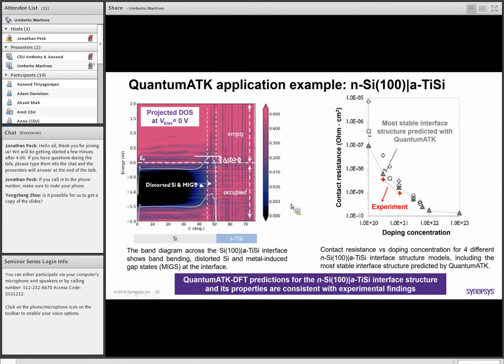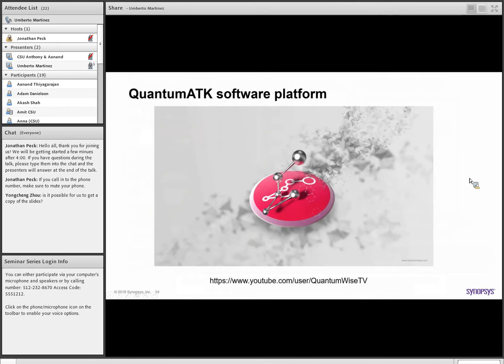And here they basically did more or less the same analysis shown before. They do this projected density of states analysis that shows a nice band bending and these metal-induced gap states. And then by studying many different interface structures, we can calculate which one is the most stable one with the tools that we have, and then compare to experiments. And here they saw some nice comparison.